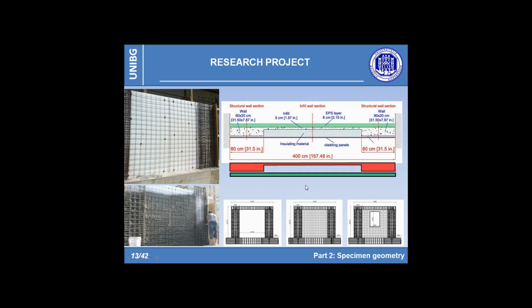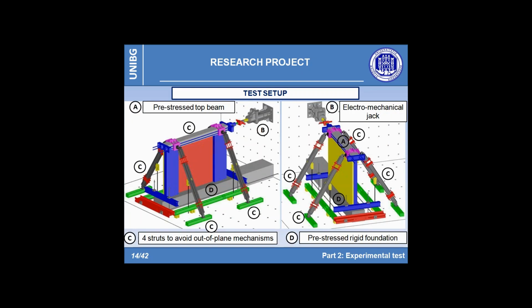The specimen, being a typical portion of the external building envelope, is constituted only by the EPS panels and the shotcrete layer. So, 3 pseudostatic cyclic tests have been conducted on the previous full-scale specimen. The experimental tests have been performed by imposing a displacement to the top beam by means of an electromechanical actuator connected to a rigid wall used as a reaction structure.